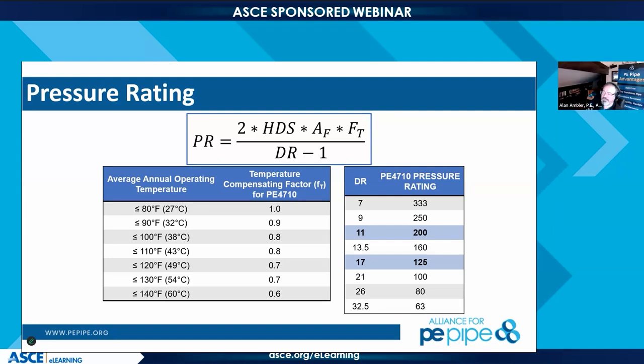Yes, Alan. So Richard, this is just additional information of our knowledge of the pipe itself. In the majority of applications for municipal installations, your buried installation is going to be well below the 73 degrees or stable at 73 degrees as we're seeing it. So you're not going to see a temperature fluctuation based on the installation temperature of the soil surrounding the pipe. It may, if you actually see large fluctuations in the conveyed fluid, which you need to pay attention to. And then also from an environmental aspect, we're